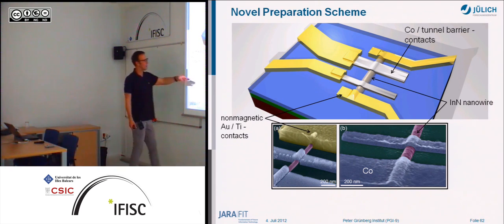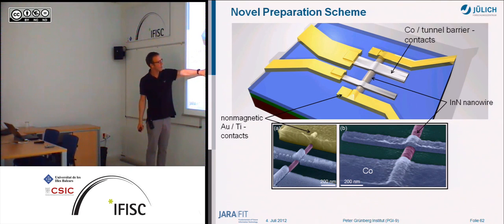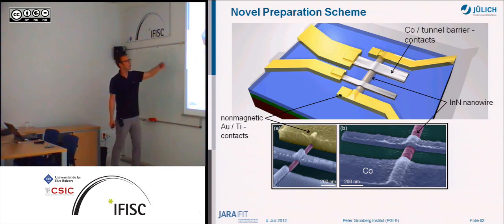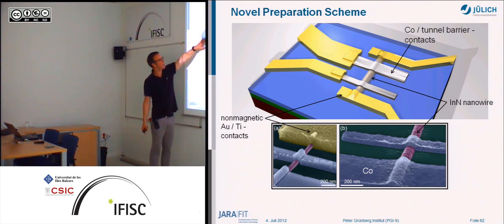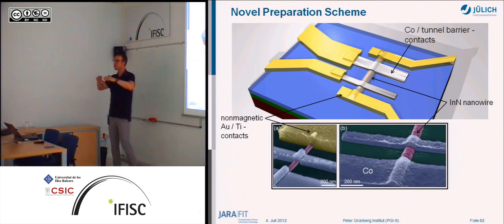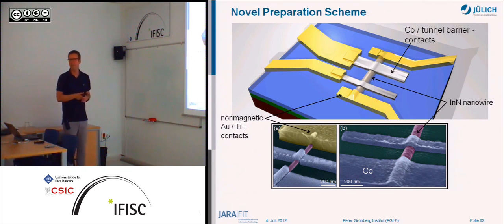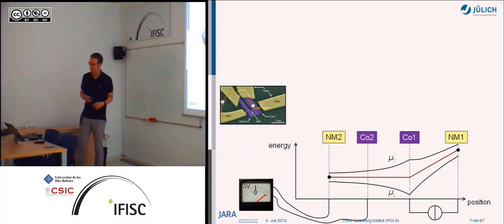The problem you have here is the nanowires are quite big, and if you have just very thin cobalt electrodes, you see that they're interrupted here. It's simply because of preparation reasons. For that, we developed a special technique to first cover the nanowire slightly so that the nanowire is kind of swimming in this dielectric. Like a trunk of a tree swimming in the ocean, you see just the surface of this trunk. By covering part of the nanowire, we can have a smooth coverage of the nanowire, and then we get a nice contact to a ferromagnetic electrode.